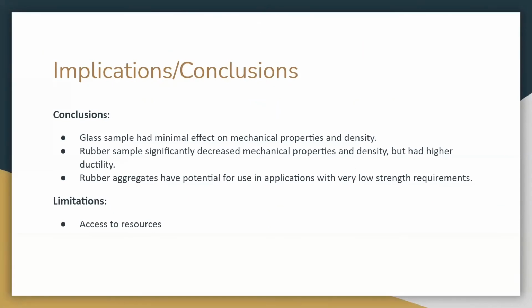In conclusion, the glass sample had minimal negative effect on the mechanical properties and density in comparison to the control mix. The rubber mix, however, had a significant decrease in density and mechanical properties. Due to this reduced density and strength, rubber aggregates have potential use in applications that only require low strength but high ductility. The main limitation during the experiment was the availability of resources and time. The number of samples tested was not large enough to make a definitive conclusion about the rubber sample's mechanical properties.